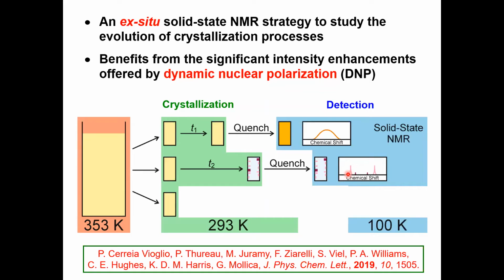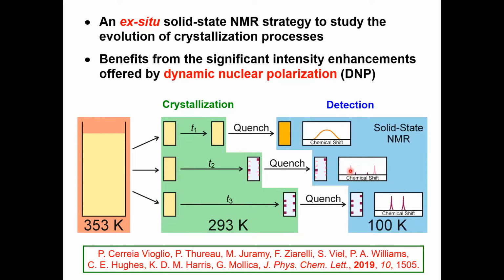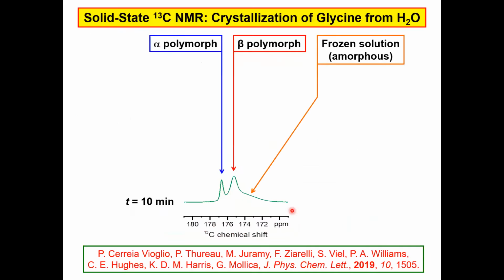And as I said, we can then do very detailed NMR experiments at the low temperature on these quenched crystallization systems. So we get the time dependence by looking at each of these snapshots of the crystallization, each one quenched at a different point in time during the crystallization process. Very briefly, here's just one example from this paper, crystallization of glycine from water. After 10 minutes in this experiment, after quenching, we can see we have predominantly the beta polymorph, some amount of the alpha polymorph, and a lot of the uncrystallized glycine in this frozen solution.